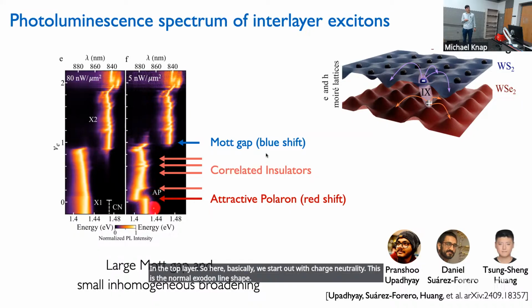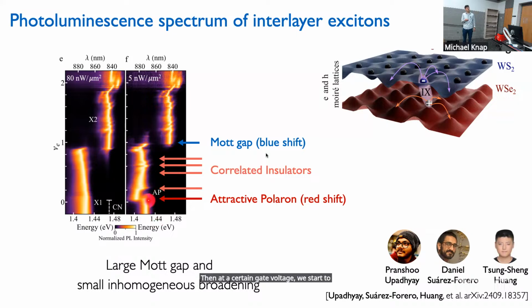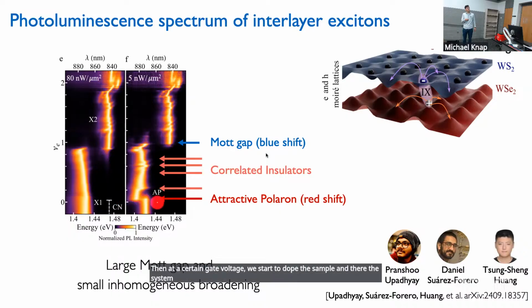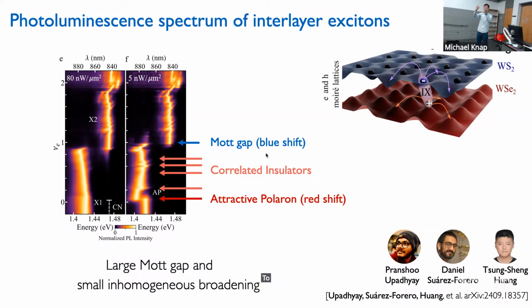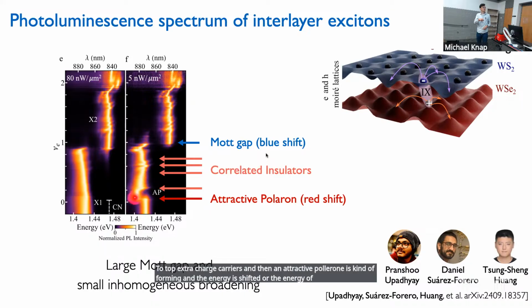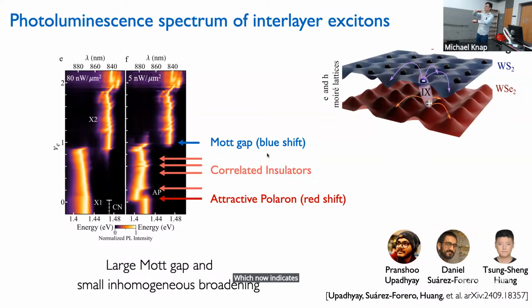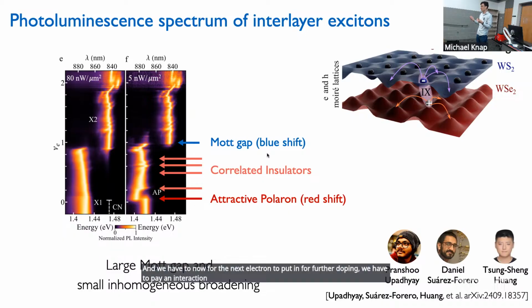Then, at a certain gate voltage, we start to dope the sample, and the system shifts here to lower energies, and this is the formation of the attractive polaron, we believe. So what's happening here is that we start to dope extra charge carriers, and then an attractive polaron is forming, and the energy of this resonance is shifted to lower energies. Then there's a little bit of squiggling going on, and when we increase the gate voltage a bit more, all of a sudden there's a large jump in the spectrum, which indicates that we have filled the top layer with one electron per site, and for the next electron to put in for further doping, we have to pay an interaction energy, which is the Mott interaction energy. So that's the Mott gap, which results here for this specific material in a blue shift.